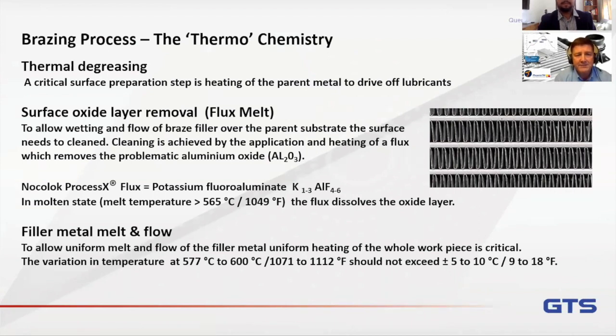Right. And this is basically the use of, for instance, in the Nocolok process, potassium fluoroaluminate, which is a chemical that basically eats the oxide layer and leaves the aluminium surface clean for the brazing process to occur. So the product will obviously be either sprayed or impregnated with the flux material, which then will melt at 565 degrees. That is critical to the surface preparation before the braze process itself. And then obviously the filler metal has to melt and flow.